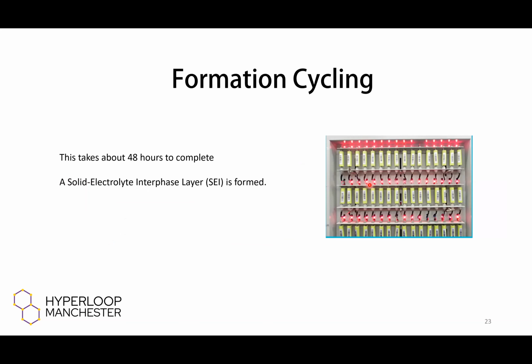But after all this, there's a final stage. Once you've done the manufacturing of it, you're not yet finished in making batteries. You have to do something called formation cycling, which is where you charge the cell under specific conditions. They could be under different temperatures or up to certain voltages, and you're holding the cell in those conditions, or, I don't know, cycling the cell in between those conditions for a few hours or a few cycles. This actually requires quite a lot of energy to do. You have to basically be charging every single cell that comes out of a factory, I don't know, a couple of times, 4 or 5 times at least, I guess.